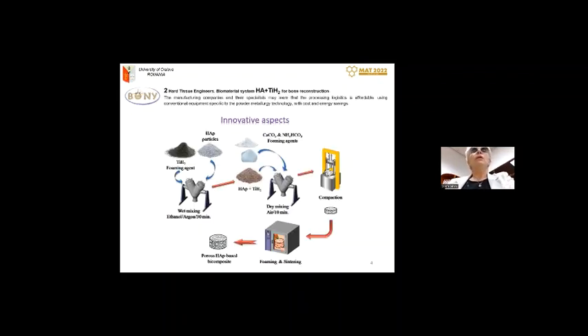So we decided to work with this system, which is actually quite well known, hydroxyapatite and titanium hydride. We selected it because it has a very attractive property regarding the foaming process. During the heating, the hydrogen, as you will see, will be released. So we can control the porosity of the material from this point of view. Because everybody in the biomaterials field knows that bone is not an isotropic material, it is quite anisotropic. So we need to play with the porosity in order to obtain a biomimetic structure related to the cortical tissue or to the trabecular tissue.